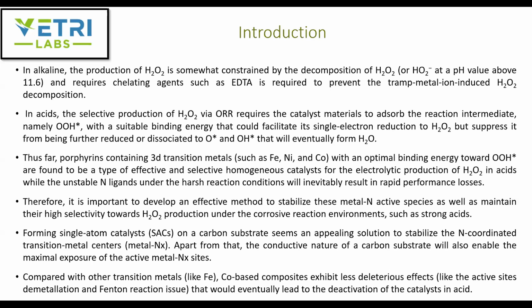but suppress the further reduction to water. Based on the different catalysts that have been used, porphyrins containing 3D transition metals such as iron, nickel, and cobalt, with an optimal binding energy towards OOH, were found to be effective and selective homogeneous catalysts for peroxide production in acidic media. However, these unstable nitrogen ligands under harsh reaction conditions inevitably lead to a rapid performance loss. Therefore, it is important to develop an effective method to stabilize these metal nitrogen active species as well as maintain their high selectivity towards peroxide production in highly corrosive environments such as strong acid.